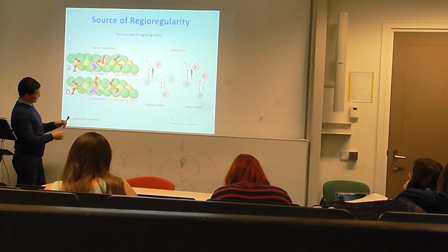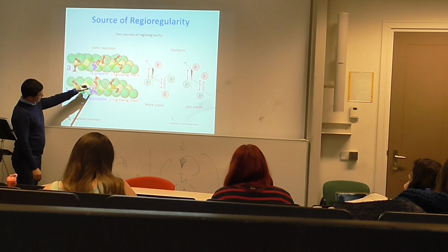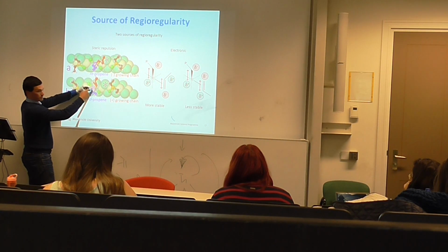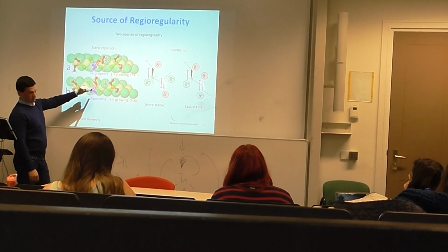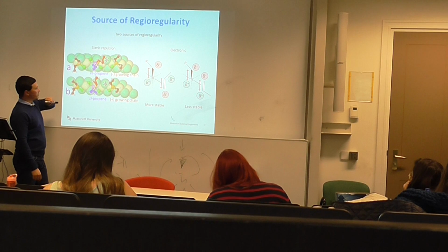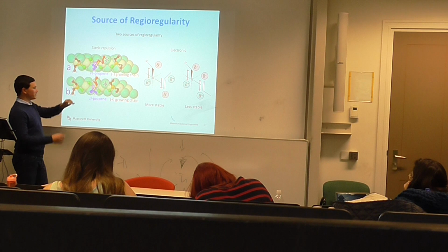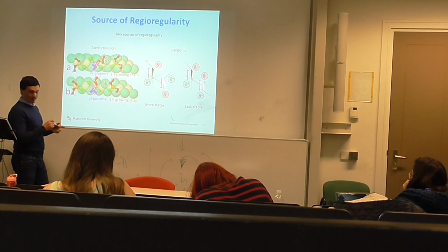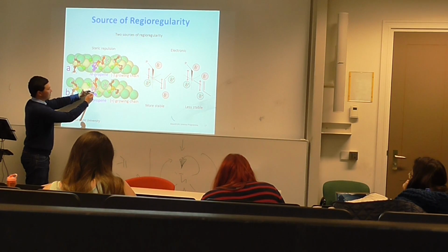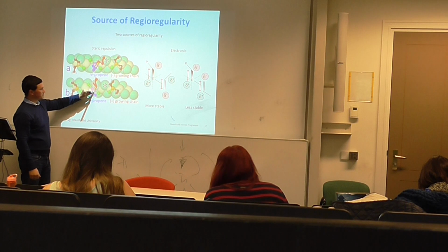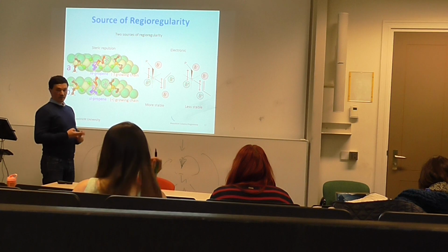Now, let's say here is where the methylene is. Your methylene will be here, okay? If I point in this direction, your methyl group is going to point towards the catalyst. So it's less favorable because of the steric repulsion between the methyl group and the catalyst itself. So it's energetically more favorable to have the methyl group pointing in the opposite direction. Okay? That's one. Second, electronic.